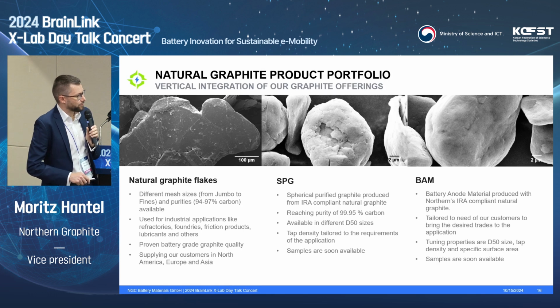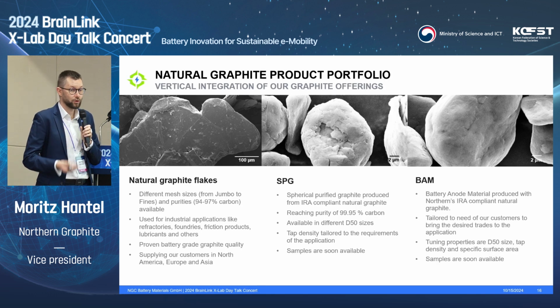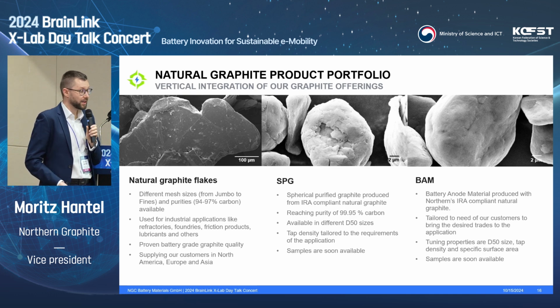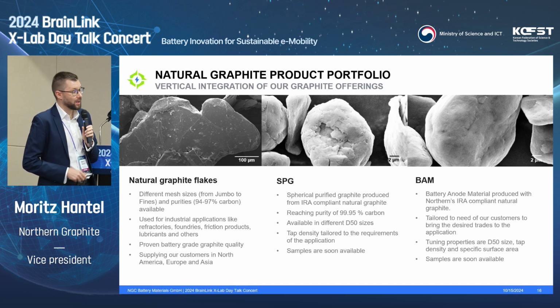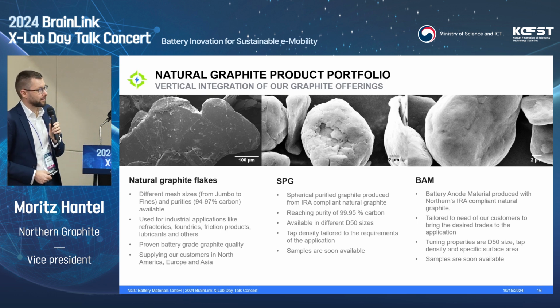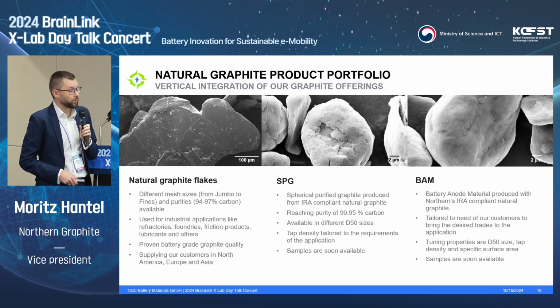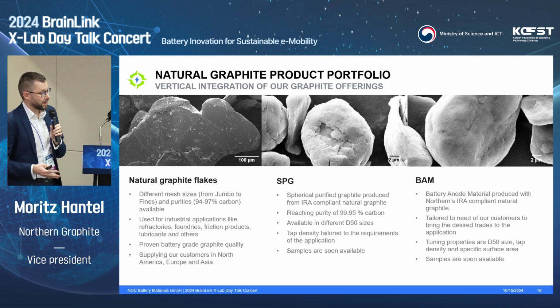Just a little summary in this regard: natural graphite flakes come in different sizes and purities. They're still very important for industry applications, like refractories, foundries, friction products. So in other words, a lot of our modern technology requires graphite in the processing. But what we are now interested in is going more into vertical integration and getting natural graphite-based battery products into the market which are not out of China, to diversify the market and supply chain. So we have the SPG, where we can tailor to the needs of the customers in terms of tap density and size. And then for sure the BAM in the end, where beside tailoring the D50 and tap density, the coating which is applied also defines the quality later in the material.